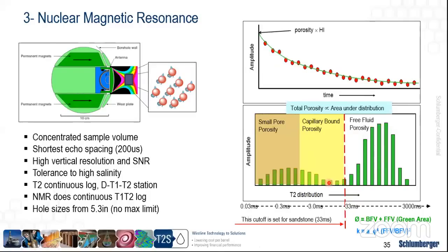By looking at this spectrum of the T2 distribution, we can identify multiple things in the reservoir when it comes to movability of the fluid. First of all, by looking at the very high peak towards the later time of T2, we can identify the free fluid porosity and how much free fluid we have in the pore space. By looking at the shorter T2, which typically comes at around 0.3 to 3 to almost 10 milliseconds, we can identify how much bound fluid we have.